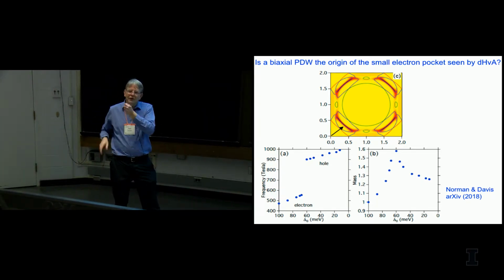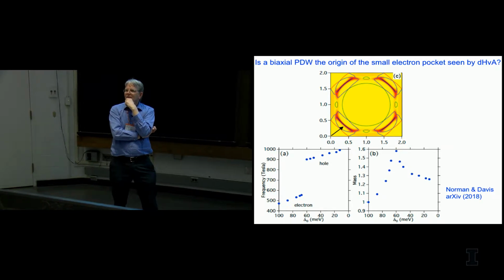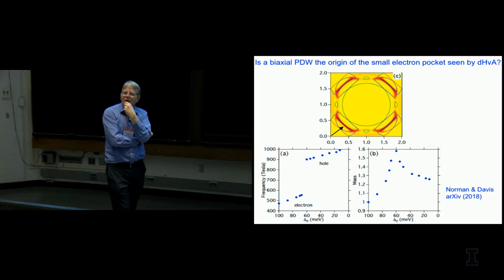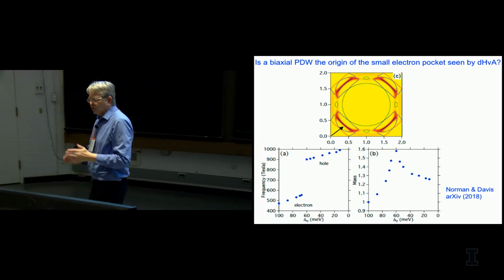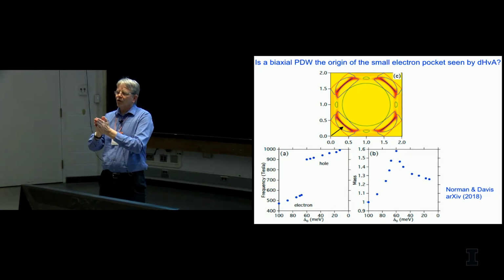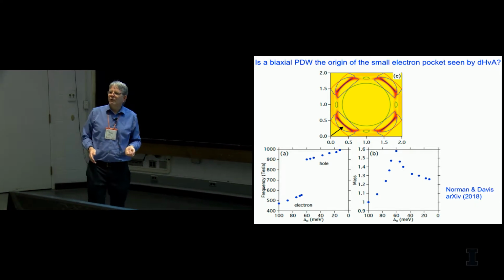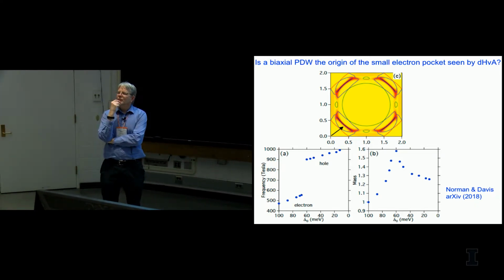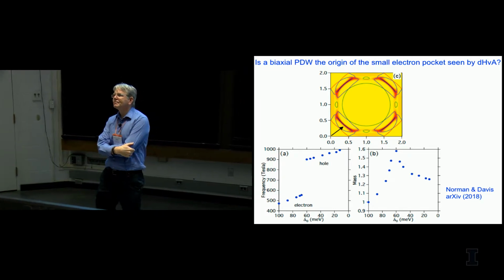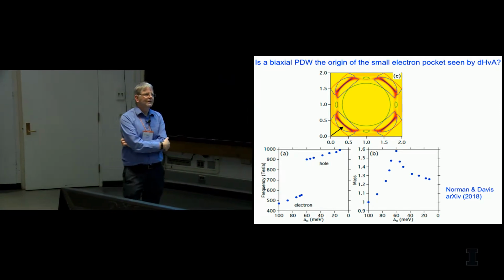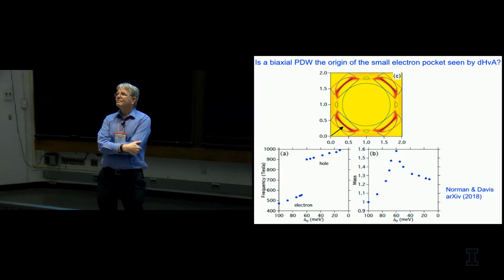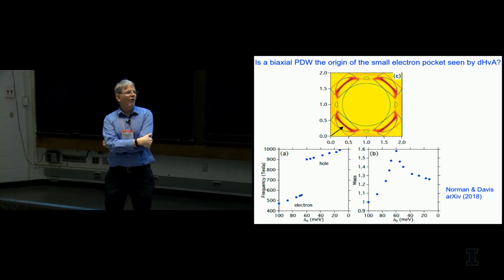The question, though, is because of this, people have speculated that this half-filled state is a Mott state, and therefore when you dope it, which they do by ion gating, or basically by voltage biasing, that maybe you get some sort of unconventional superconducting phase. My feeling, and my colleagues like Alan MacDonald have been talking about it, I think it's phonons. The reason is that if I twist this material, the electronic structure is extremely sensitive to twist angle, and therefore you expect a very large electron-phonon coupling, very similar to what you see, say, in magnesium diboride. So my bet is on phonons, but I could be wrong. The Tc is low, about 1.7 Kelvin. But it could be a cuprate analog. I may be wrong.